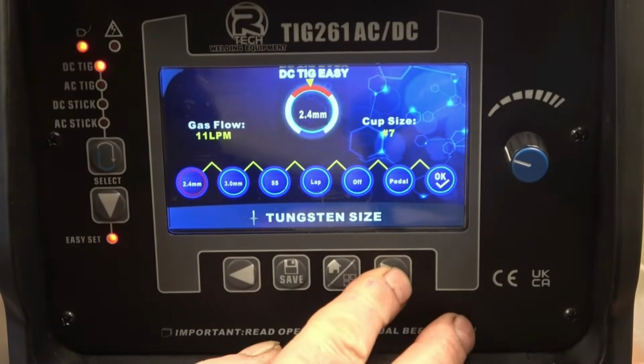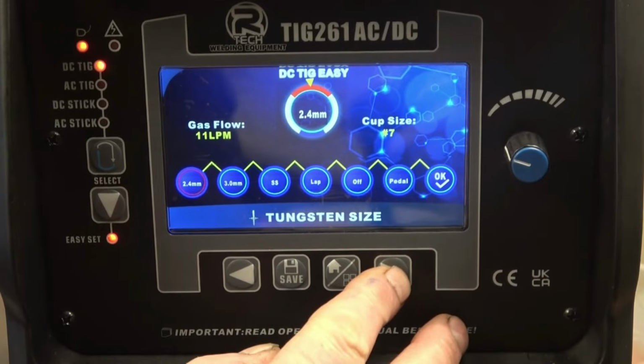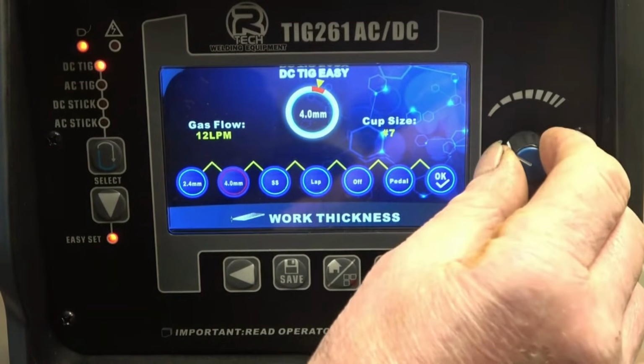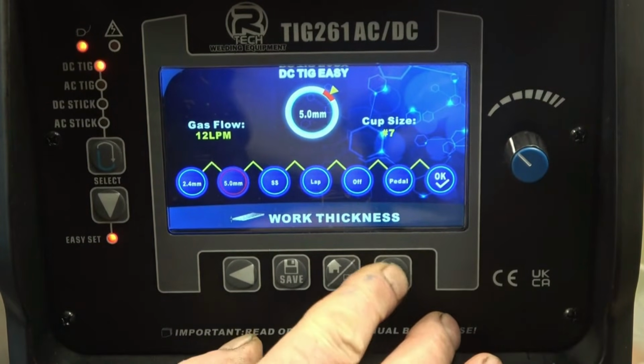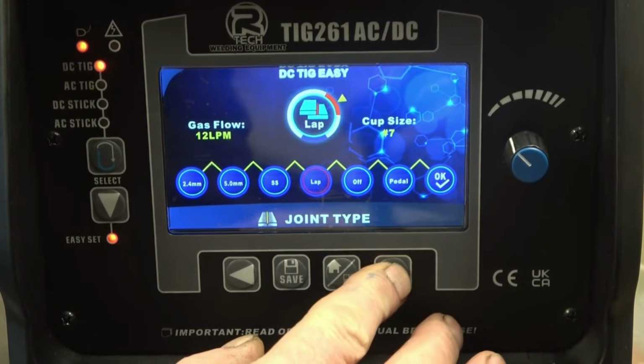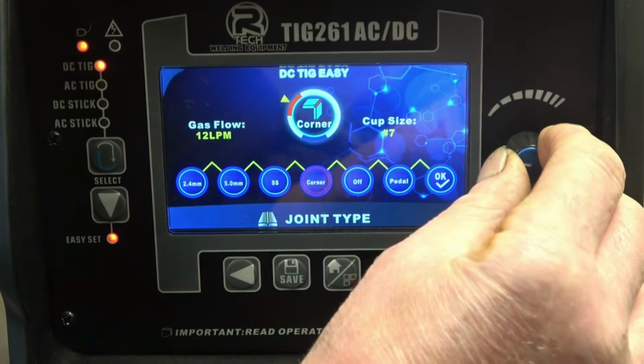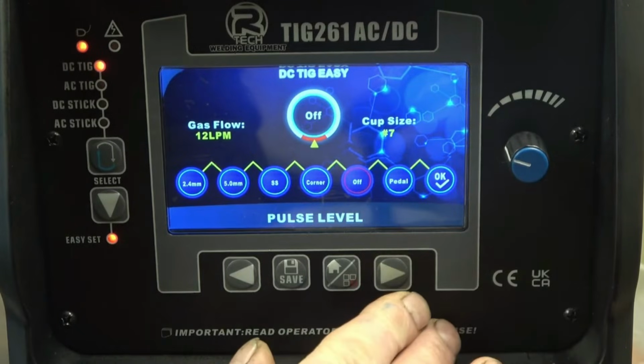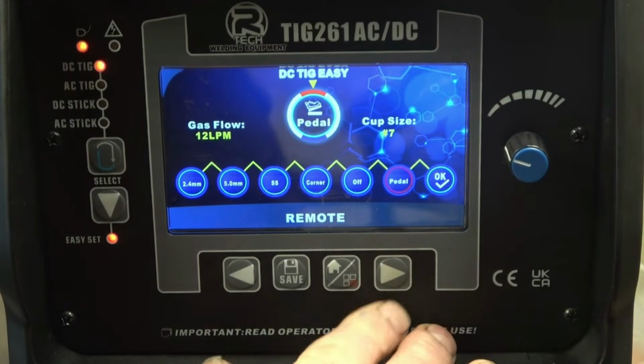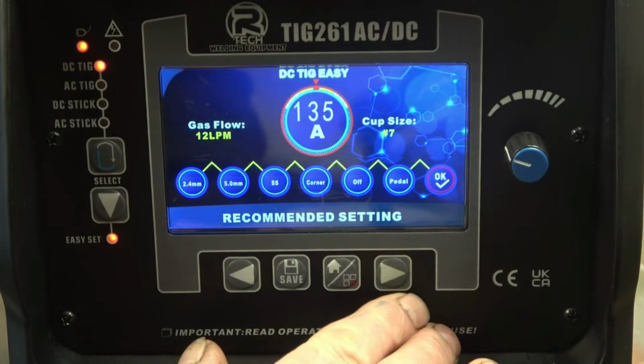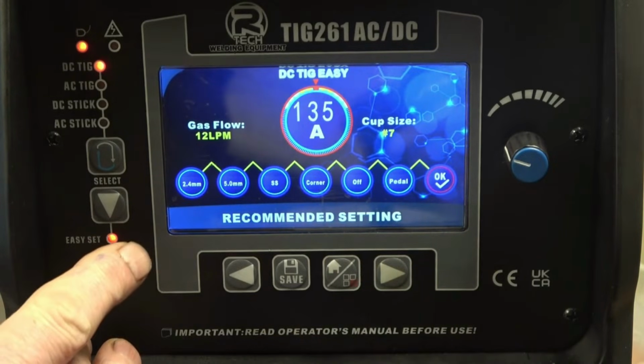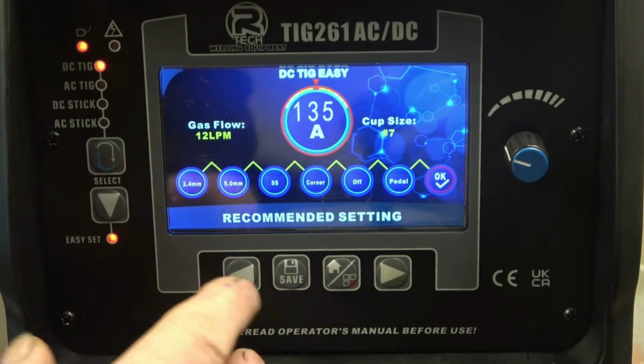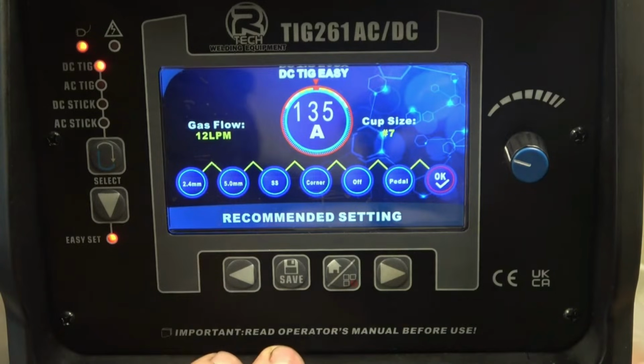We're going to go up now to some thicker material, still on the same 2.4 tungsten. We'll go up to 5mm stainless steel. We're going to do a corner joint this time. Pulse is off, pedal. Okay, so it's 12 litres a minute argon, 135 amps with a number 7 cup. I can still run the 2.4 tungsten on 135 amps, no problem at all.